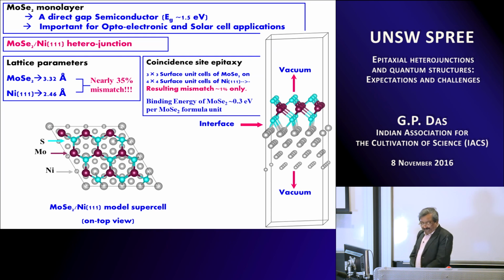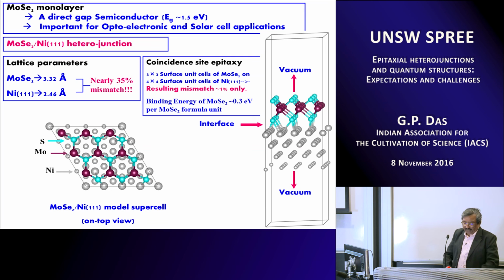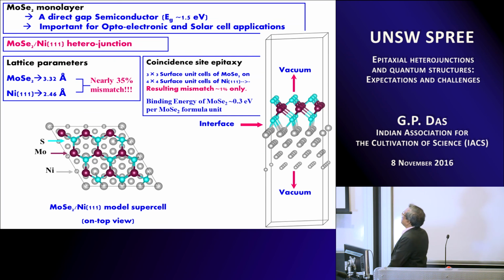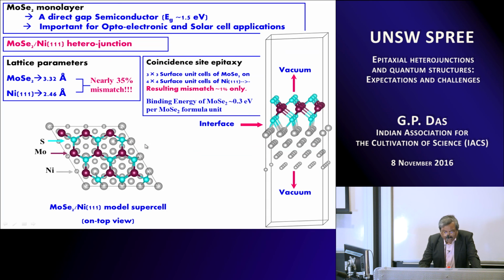Okay. Now when you make a heterojunction of MoSe2 on nickel 111, because of the lattice mismatch, about 35% lattice mismatch, again what we did is this coincidence site epitaxy, which I already told you earlier for the case of silver on silicon. So here the 3x3 surface unit cell of MoSe2 is put on a 4x4 surface unit cell of nickel 111, and the resulting mismatch becomes almost negligibly small. The binding energy is about 0.3 electron volt per MoSe2 formula unit, and this is how the top view shows. You can see 1, 2, 3, 3x3, and here it is 1, 2, 3, 4, 4x4. So this is the side view of the interface of the MoSe2 quasi 2D layer on the nickel 111.